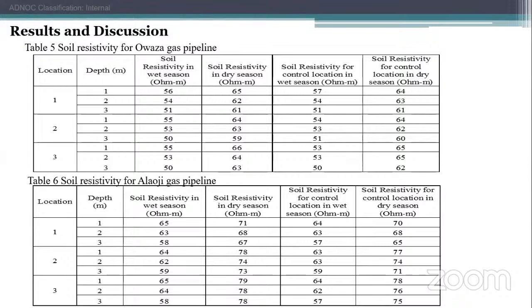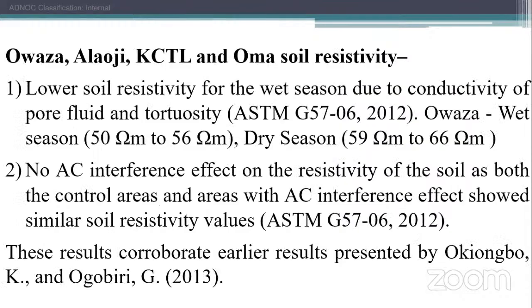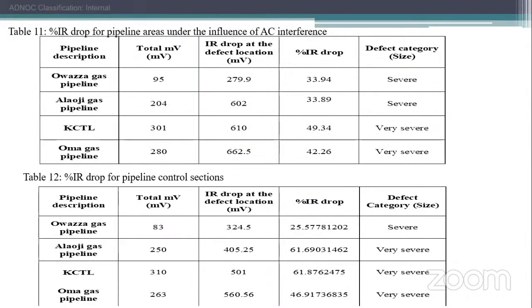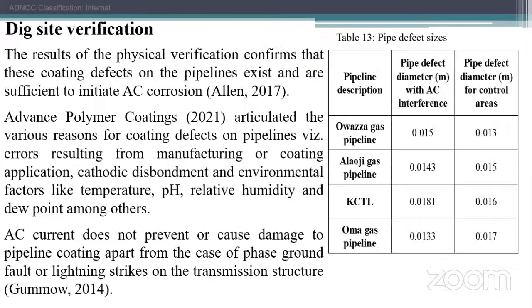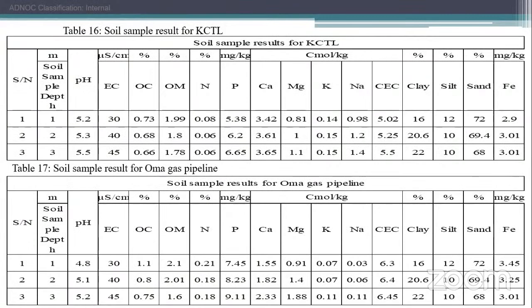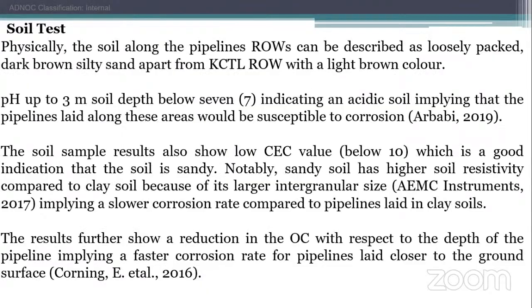Okay, thank you. So the results: the resistivity was lower for the wet season compared to the dry season. Then the AC current was measured. Then also the coating defects. It was also realized that we had defects in this coating. Then the soil sample test results, the pH was also measured. Different factors were considered: the cation exchange capacity, the positive ion holding capacity of the soil, and all that.